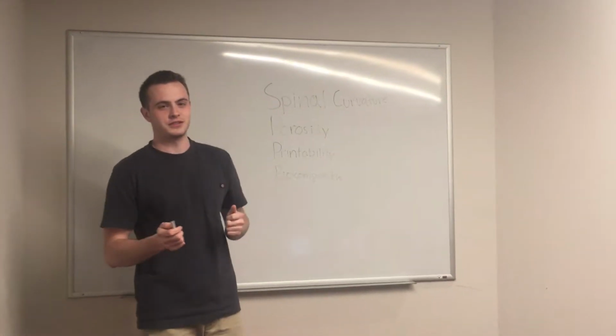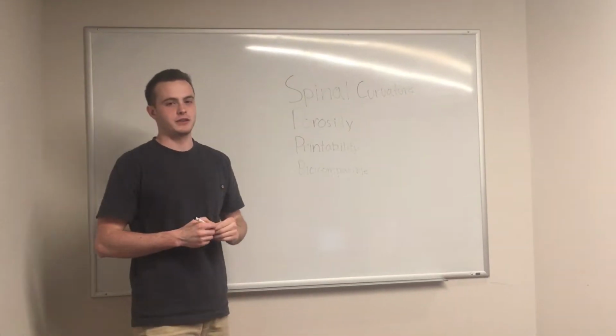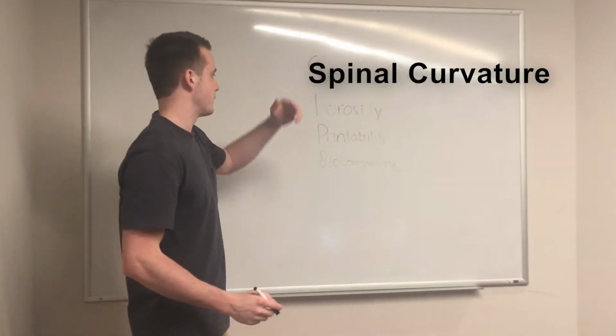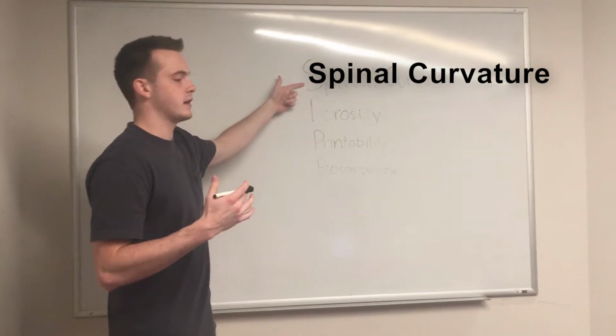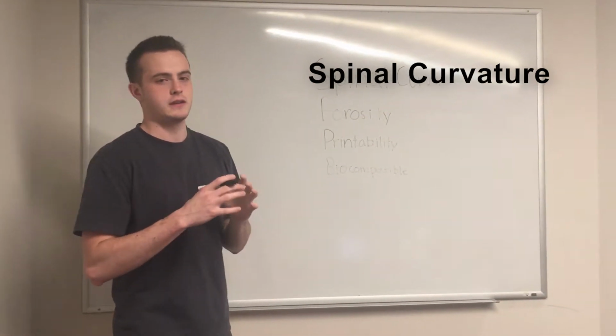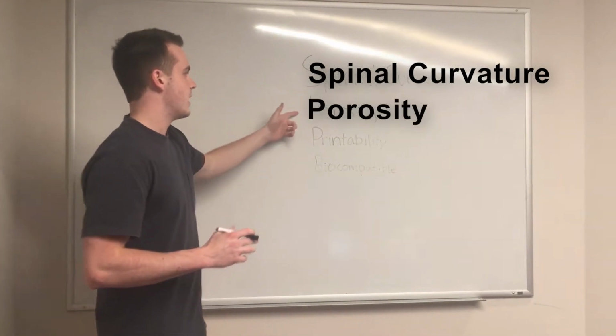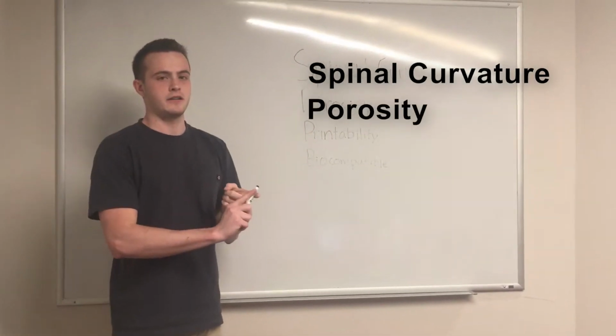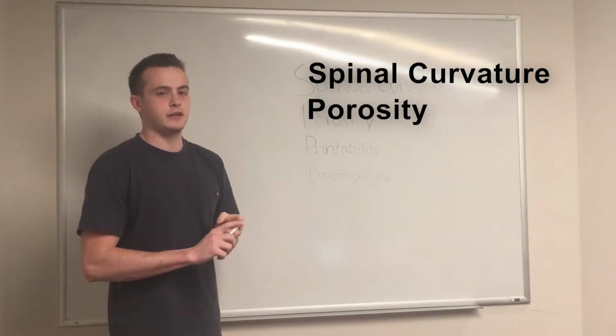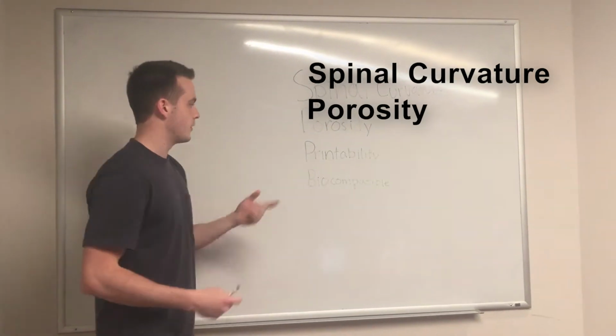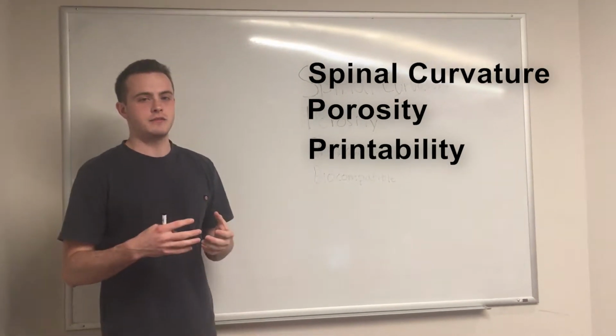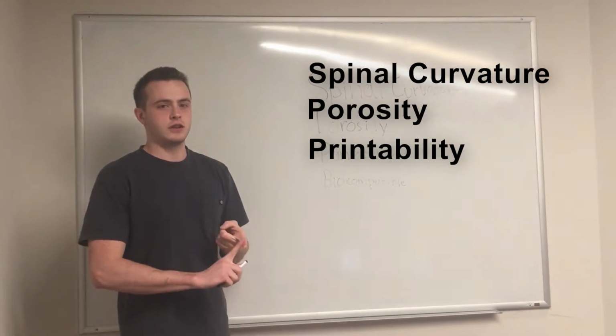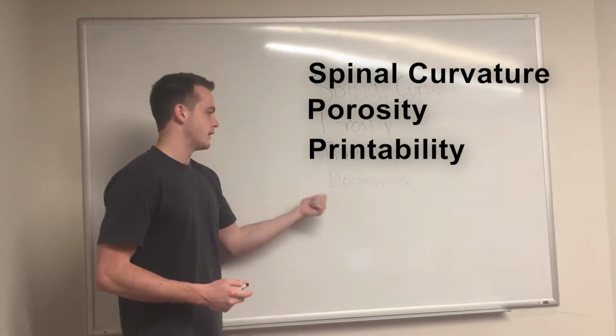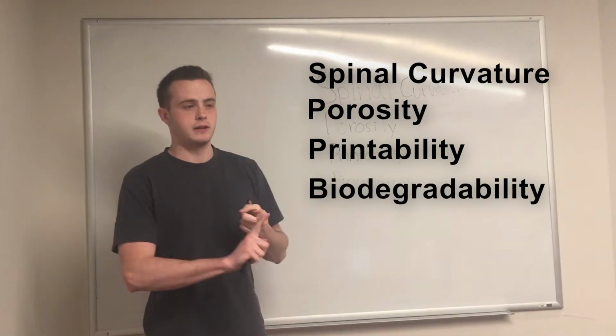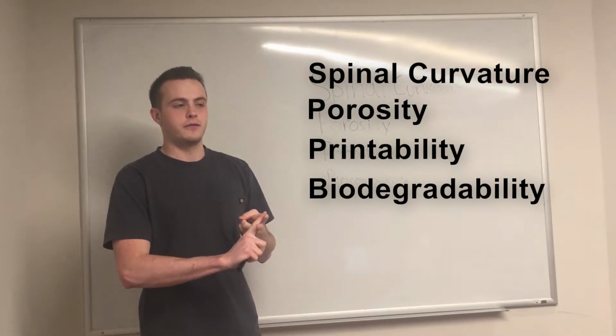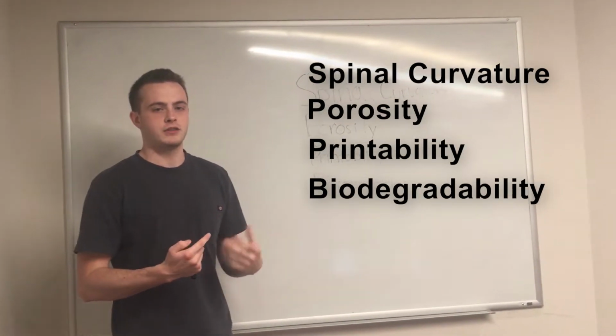In addition to the chemical considerations, we also had several design parameters that we needed to consider in making our design. The first one, that our patch would match the inner spinal curvature of the nerve bundle and it would fit within the inner spinal canal. In addition, our porosity needed to be tailored to block out macrophages and biological inhibitors, and we tailored that through our cross-linking density. The third, printability, has to do with the viscosity of the printer feed, and that has to do with the concentration of polymer in our hydrogel feed. And finally, biocompatibility has to do with the polymer that we chose and the Irgacure photo initiator that Jack talked about with our polymer chemistry.